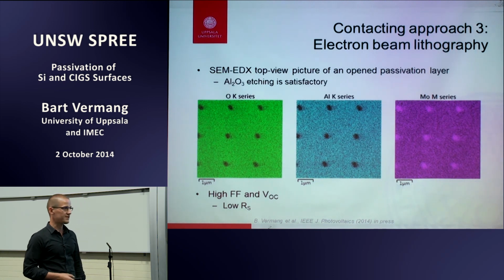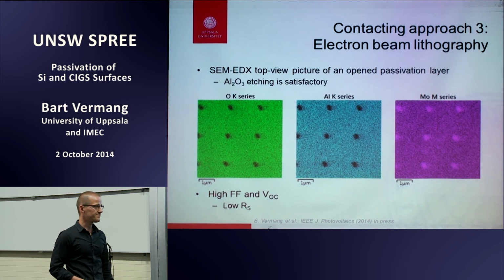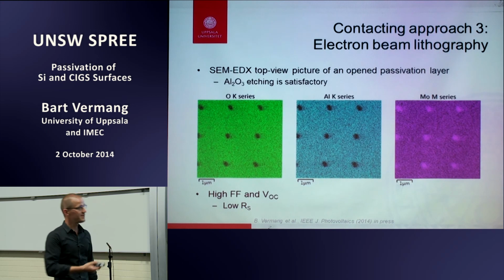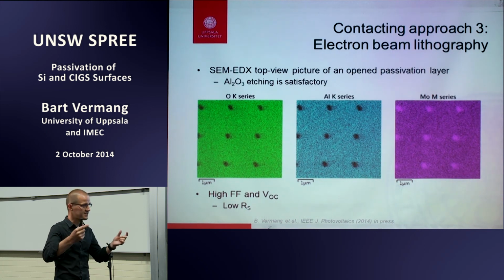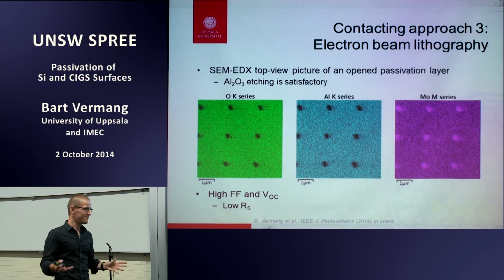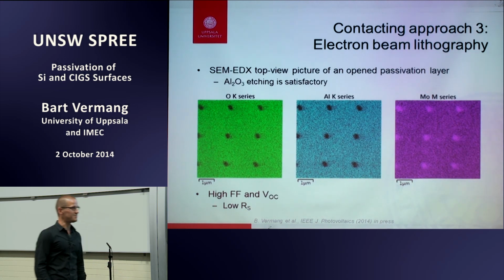But it's even being used in other technologies for all kinds of barrier layers, aluminum oxide. It's even used in CIGS solar cells. So indeed you use the sodium from the soda lime glass to optimize your CIGS layer. However, that's a very random process. So in industry, what they like to do is to have a barrier layer to block the sodium and put some sodium fluoride themselves. That way they completely control the amount of sodium they put in the CIGS layer. And the best barrier layer they found out is aluminum oxide, ALD aluminum oxide. For cost-effective reasons, they're typically using silicon oxide nitride, PECVD, but ALD aluminum oxide is much, much better. So that's maybe the best one.